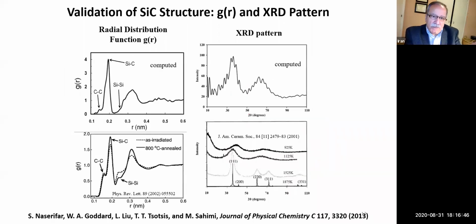So we compute various properties of the structure. On the left, you see the radial distribution function. On the top is computed, at the bottom is measured, and they look completely similar. And indeed, you see that in addition to the silicon-carbon bond, the main peak, you also have silicon-silicon and carbon-carbon, and that's why the coordination number, the connectivity, is less than what it should be.